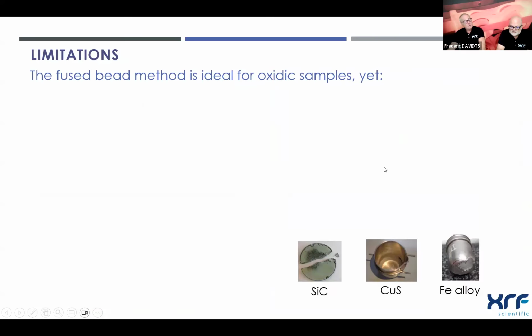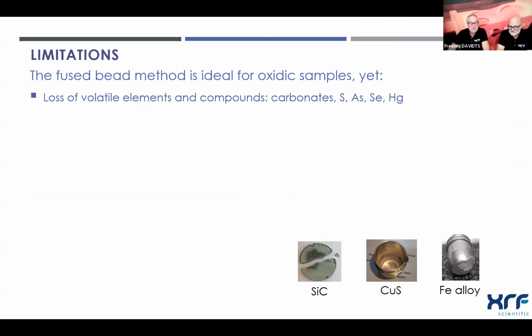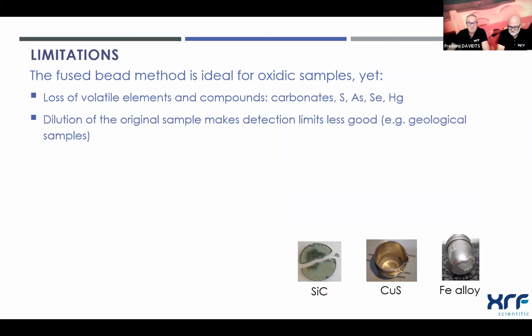Now, there are a few limitations, of course, also nothing is perfect. Still, there are solutions. So the fused bead method is really ideal for already oxidic samples. But what we have to bear in mind is that when there are volatile elements like sulfur, arsenic in our sample, we may lose them. The same for carbonates, of course. People working with cement will know this. The cement furnace, we will lose carbonates by high temperatures. The same happens in fused beads. And also the dilution of the original sample makes the detection limits less good. This is, for example, important in geological samples. And we cannot analyze elements lower than fluorine, or equal to or lower than fluorine.